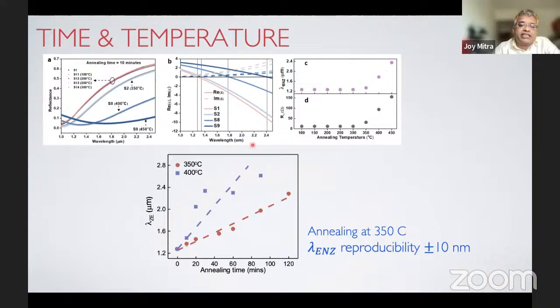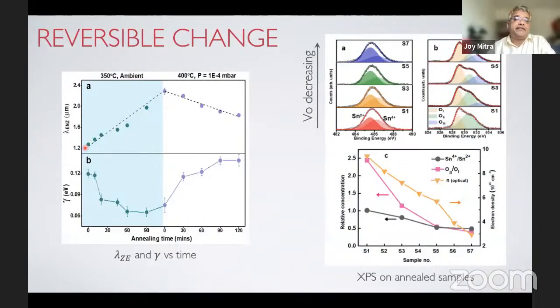We did the optical measurements and calculated the lambda ENZ. And what we saw was that it was absolutely reproducible. The change in the number density, and consequently the change in the lambda ENZ, was absolutely reproducible up to plus or minus 10 nanometers. Reproducibility at higher temperatures was a bit more erratic, and therefore we stuck for the rest of our work to annealing at 350 degrees. Not only did the films become more resistive as we annealed them in oxygen, it was also reversible. If you then annealed the film subsequently in vacuum, oxygen was going out of the system and oxygen vacancies were being created, and the film again became more and more conducting, and consequently the lambda ENZ went on decreasing.